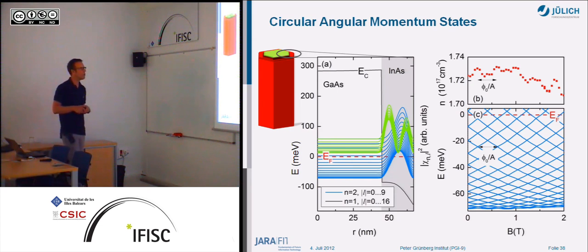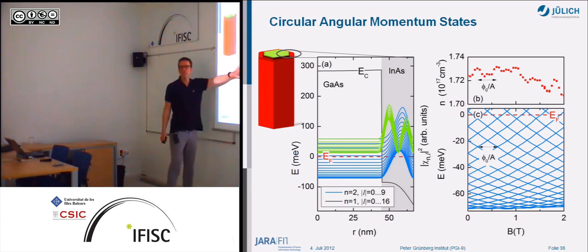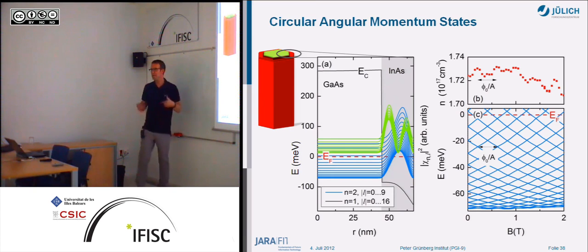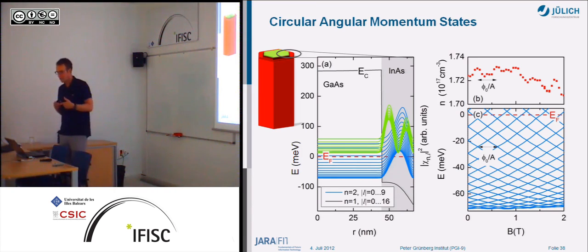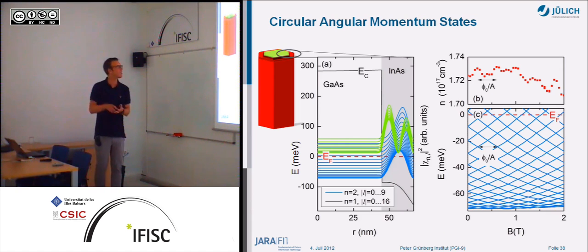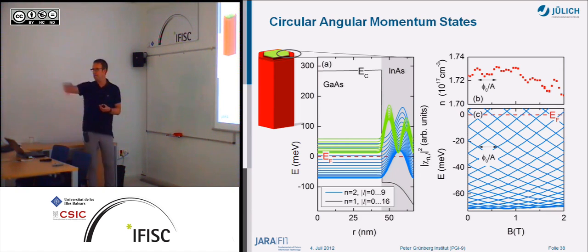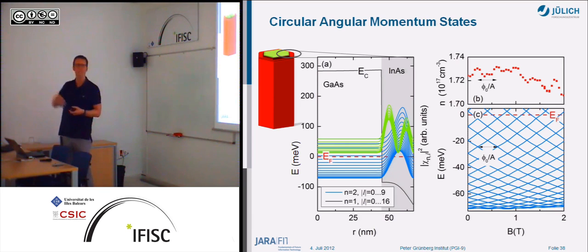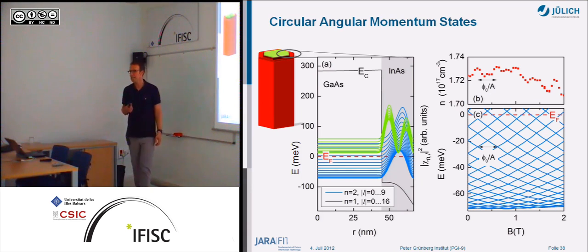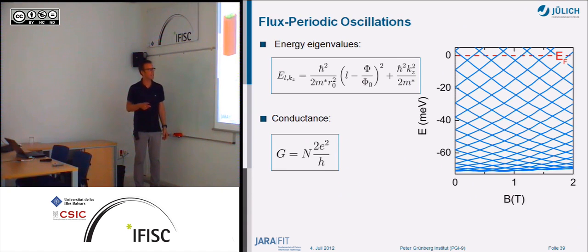So we have to look at how these states change with magnetic field. Because we have this quadratic flux dependency, we get this energy spectrum here. So these are the levels we have here. And if we now apply a magnetic field, because of this flux we put into that wire, we change the energy levels with B squared, basically. And that's what you get. So you get this mesh of states here. And the question is now how we get the regular oscillations in the conductance.